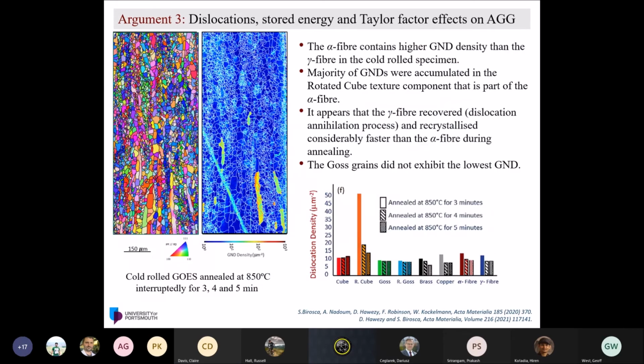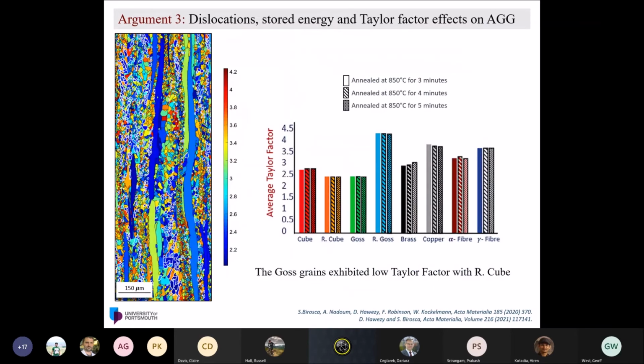But in fact, we tried to understand if Goss grain has the highest dislocation density. In fact, we couldn't find that. Rotated cube was considered to have the highest GND density, as we show here. However, when you look at the next slide, for calculating the Taylor factor, the Goss was kind of equal to rotated cube and a little bit lower than the cube.